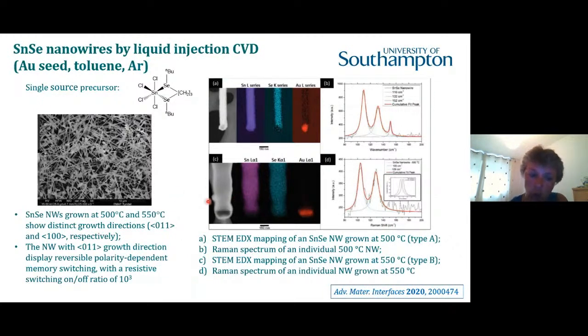And these nanowires we've been looking at, we've done some preliminary experiments, which was recently published, looking at these for applications in resistive solid-state memory, so resistive RAM for nano devices. And we see very promising data with on-off resistive switching ratios of about 10 to the 3, which is pretty competitive. So that's showing the growth of these nanowires using the same sort of molecular precursor.